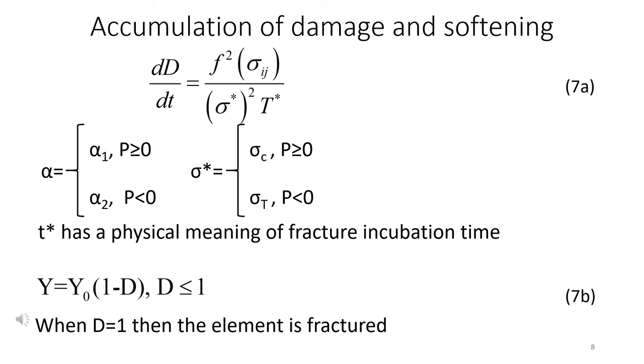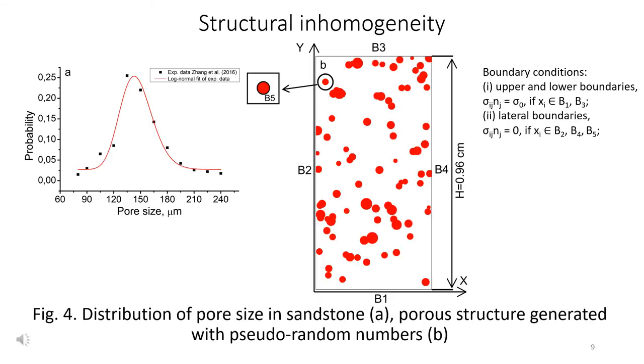The damage parameter D kinetic equation is given by equation 7a, and the softening law is expressed by equation 7b. The pores are distributed in a computational domain by a pseudorandom number generator with an assumption of spherical pores and porosity distribution illustrated in the left part of the figure. Boundary conditions are also provided in the slide.